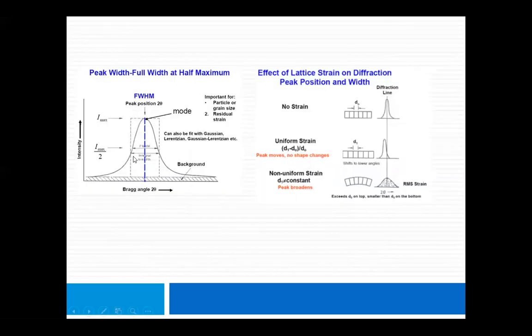But in case of nano, the width at the bottom will be increased. You can say like this, on the left side. So peak broadening will happen. Please remember, peak broadening doesn't happen only from the particle size. There are 3 reasons. One is if the particle size is smaller, peak broadening will happen. The second is stresses. If you synthesize nanomaterial powder by ball milling, a lot of stresses are there. If you synthesize by chemical route, stresses are negligible.